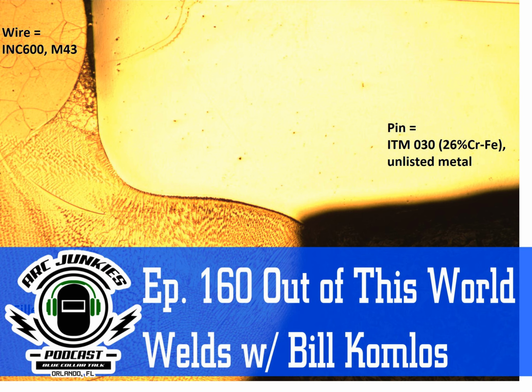And then I welded wires in the flare V groove on one side and then on the back side. So I had 2 wires going. So now the machine could pull. The problem is with the wire, you can't get it taut to begin with. So one wire is a little bit tighter than the other. And so consequently, there was a little bit of catch up, but once the other side caught on, it started pulling against these little tiny welds. And finally she broke right in the middle of the wire.